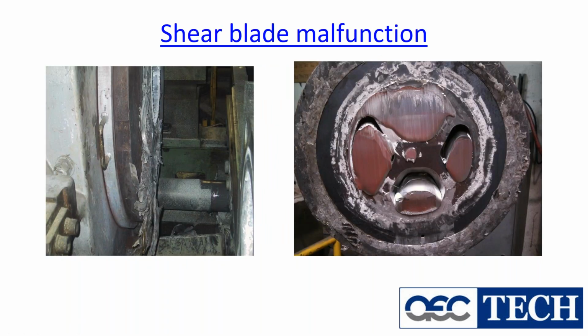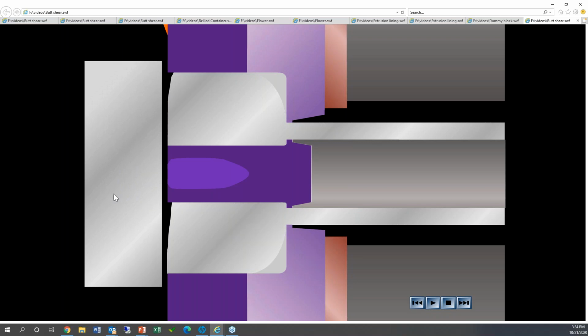When we look at a shear blade malfunction, this is what we're talking about. Build up down on the bottom and pulling the material out of the die. When we start looking at pulling the material out of the die, this is what we're going to typically see. Again, we've got a die, a bolster, backer. This is getting a little bit more into the inside of the die of what we see. We see that material getting pulled out here and here from the die. The next billet gets loaded. There's our wonderful burp cycle.